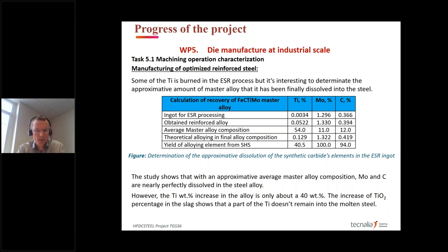So to summarize, we have to say that some of the titanium is burned in the ESR process. We can see here that the final yield of alloying element from master alloy, in this case titanium, the recovery rate was approximately 40%. Molybdenum recovery rate was almost 100%, and the carbon recovery rate was also 94%. So this study shows that with an approximative average master alloy composition, molybdenum and carbon are nearly perfectly dissolved in the steel alloy.